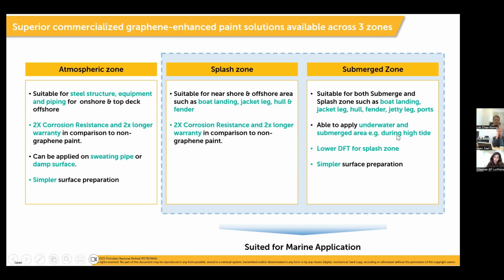And we have a solution for the submerged zone, such as boat landing, jacket leg, hull, fender, jetty legs, and ports. Now, these are areas that are completely submerged and you can still paint in the submerged area. All of these three areas now allow us to explore the possibility of simpler surface preparation and in certain cases, even lower thickness. Very specifically for the splash zone and submerged zone, these two systems that we have developed today are suited for marine applications as well.